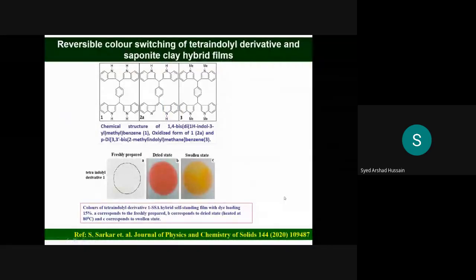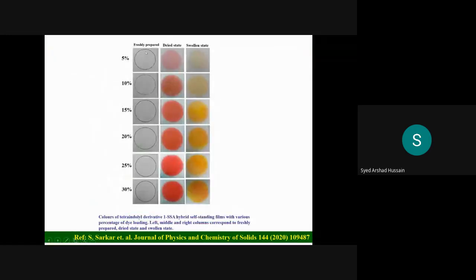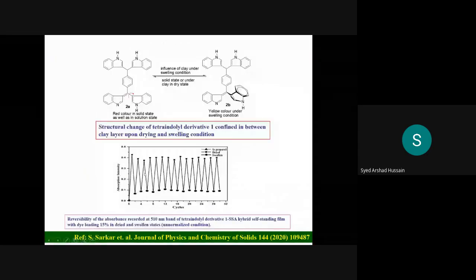Then here is another example. This is an tetraindolyl derivative, again mixed with saponite clay. In normal condition this is colorless, but in dry condition it is red, and in swollen condition you see yellow. With simultaneous drying and swelling, it's possible to get back this red and yellow color, so it's reversible in nature. We studied this color change at different concentrations, and you see it is reversible in nature.